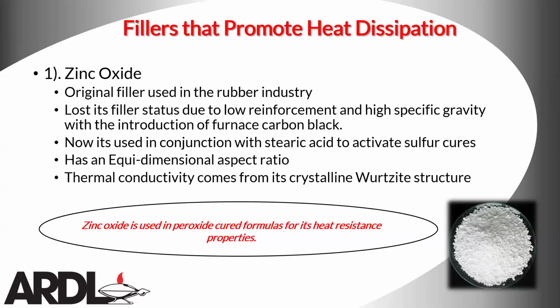So now we're going to talk about fillers that actually promote heat dissipation. The first one is zinc oxide. Most people don't think of zinc oxide as an actual filler, but if you go back to the onset of the industrialization of the rubber industry, zinc oxide was the original filler used. If you go back to the beginning of the automotive industry, tires were actually white because the first filler used was zinc oxide. However, zinc oxide does not have the same reinforcement properties as other fillers, so it lost its filler status due to that low reinforcement and its very high specific gravity with the introduction of furnace carbon blacks. Now, zinc oxide is used in conjunction with stearic acid to activate sulfur cure.